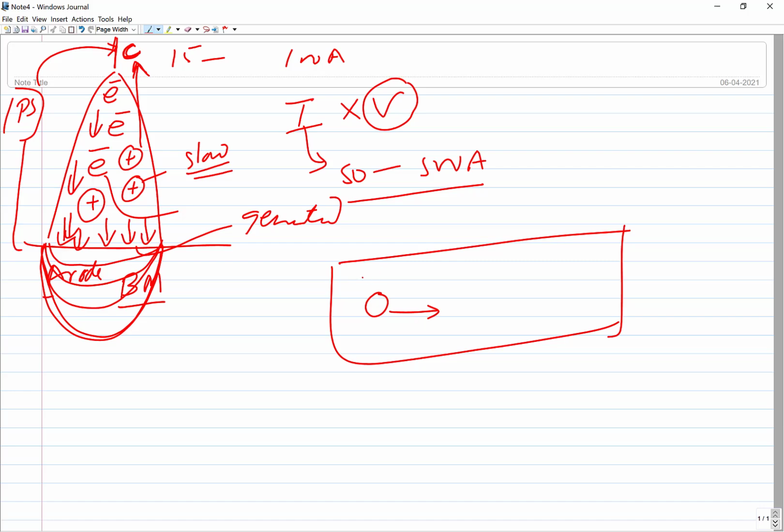So you are generating the heat at this rate VI, but since the arc is being moved at a certain speed in the welding direction, the heat delivered to a particular location will be governed by the welding speed.